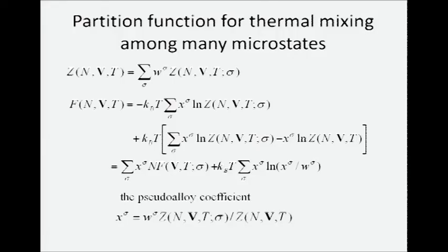So make the summation here. This term turns out to be some kind of Helmholtz free energy for individual phase. This function is quite easy to write out, but take the logarithm and derive the free energy, then we derive some formulation like this. It turns out to be very simple. The total free energy is just a little bit of summation over the individual microstates plus this term. It looks like ideal mixing, but here X sigma is decided by the individual Helmholtz free energy of the individual phase, as we write here.